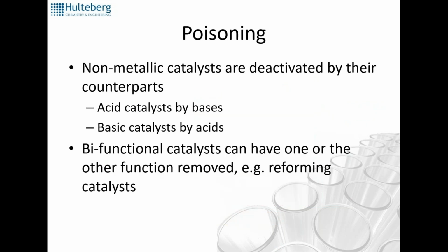If we then look at non-metallic catalysts, they're actually deactivated by their counterparts simply. So if you have an acid catalyst and you feed something that is basic, they will strongly attract and they will cancel each other out. And the same goes for basic catalysts, where an acid will knock out the active function of the basic catalyst.